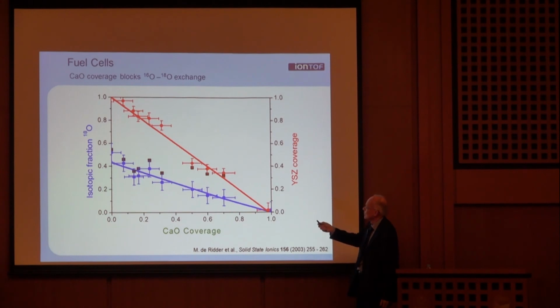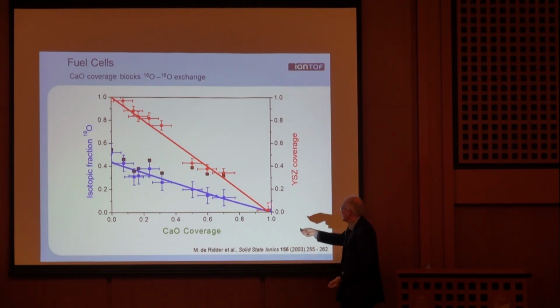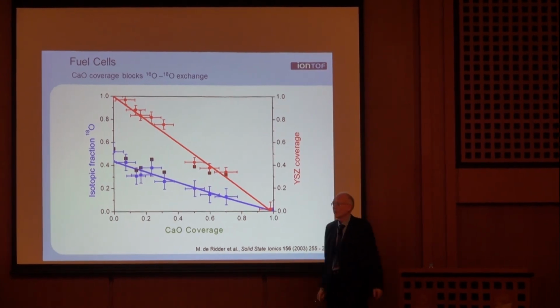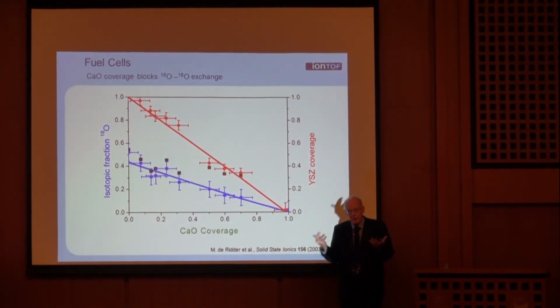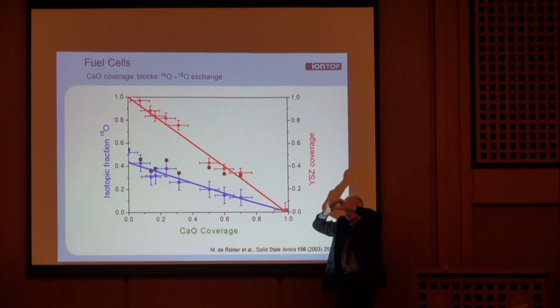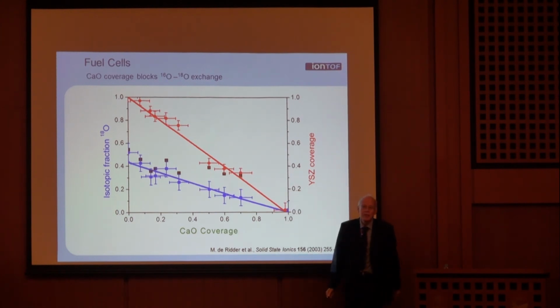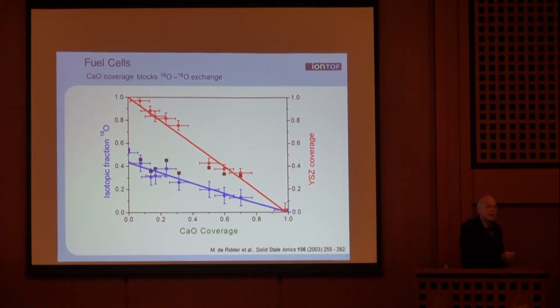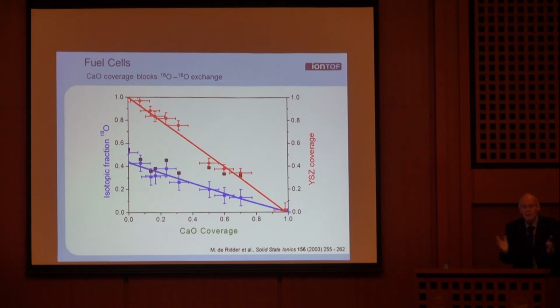look at yttria stabilized zirconia, and you see that once there is more calcium oxide, the exchange of O18, when you expose it to O18, decreases. There's no exchange reaction anymore once you have 100% calcium oxide. So the calcium oxide is completely filling up one monolayer, and it stops the exchange with O18. And that is bad when you are trying to make a fuel cell of it. So you have to play tricks to reduce that amount of calcium oxide.